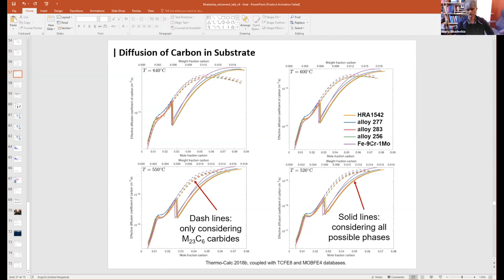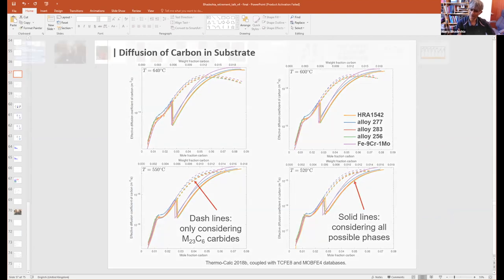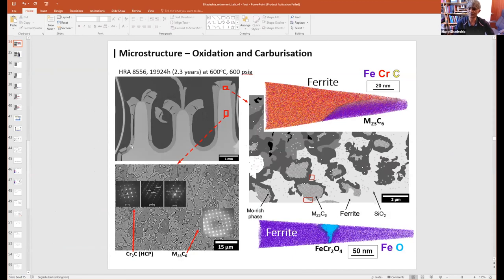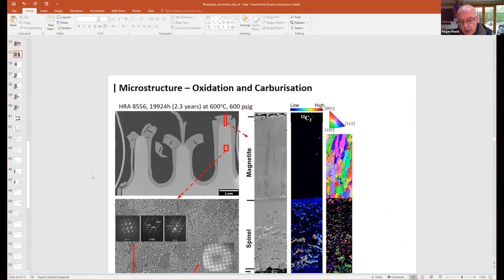Okay, and the second one was, you had chromium, et cetera, going into the oxide, but not carbon. Chromium, of course, likes to be oxidized, but there are so many defects in oxides, macro defects as well as microscopic. You may not get carbon migrating through the oxide itself, but through the defects. Yes, I think that's a really good point.